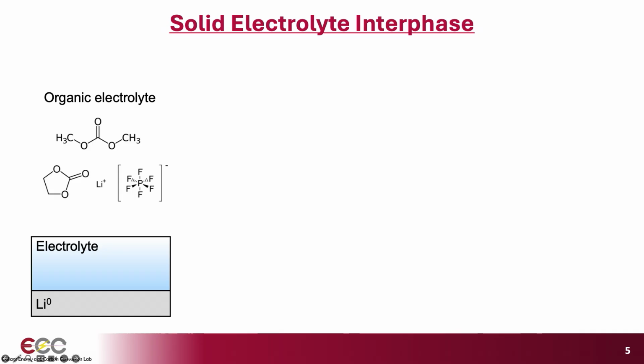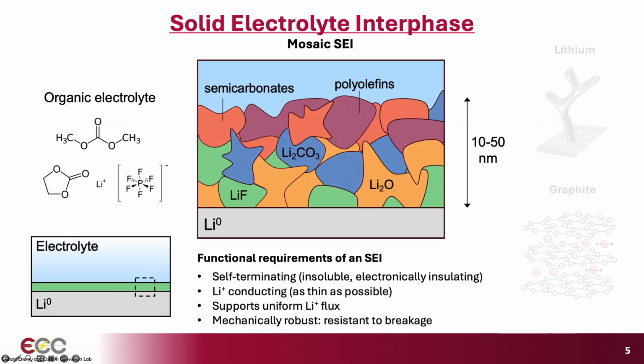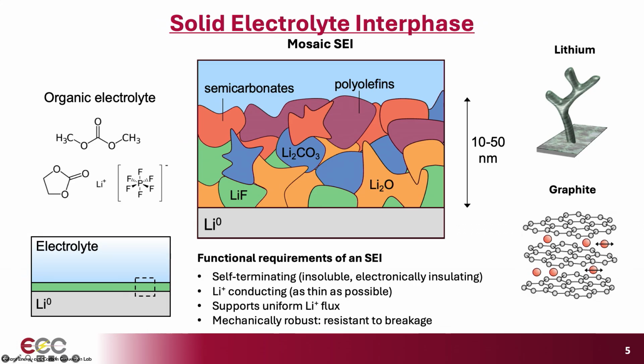So what happens when you plate lithium is it will react with the electrolyte and form a layer that is comprised of decomposed electrolyte byproducts. And this accumulates on the surface and is known as the solid electrolyte interphase, or the SEI. So the SEI, at least a good one, one that functions, is electronically insulating. So this process continues until you can no longer tunnel electrons from the metallic lithium through the electrolyte, so it's self-terminating. And that determines the thickness, and typical thickness would be on the order of a couple to tens of nanometers, depending on the electrolyte chemistry.